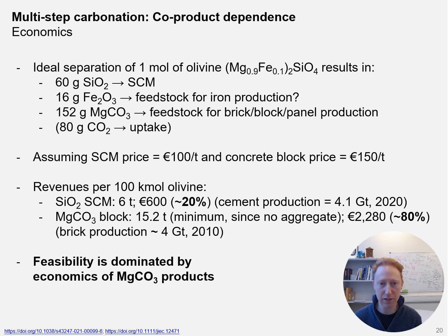For the silica-rich supplementary cementitious material, initially this material would be able to substitute silica fume in concrete products and so have a very high value. But because the total generation rate of silica fume is about 3 megatons per year, this market will quickly saturate, and so at large scale the material will be used as a standard supplementary cementitious material, competing against conventional materials like ground granulated blast furnace slag, coal fly ash, and calcined clay.